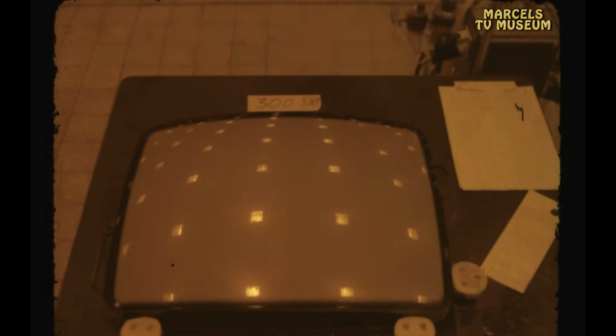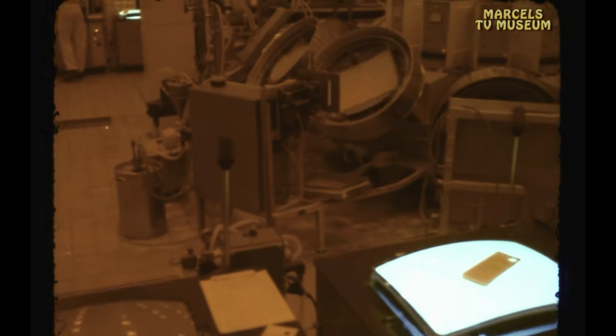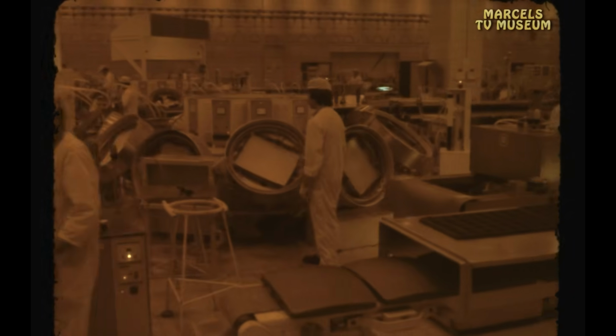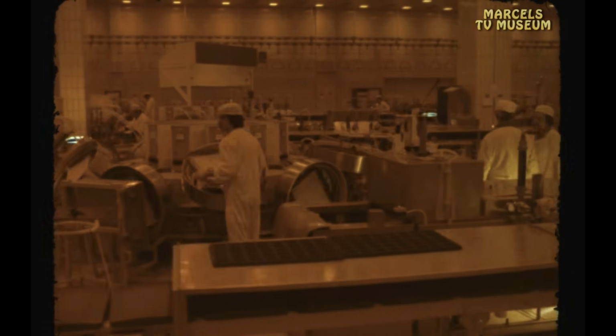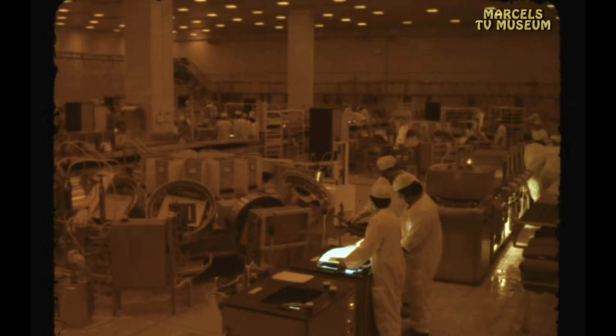Here, an accurate quantity of the fluorescent suspension for green is delivered into the rotating screen. The coating flows very evenly over the inside surface of the screen. That is why we call it flow coating. And the layer is dried under radiant heat. In the flow coat room, the fluorescent materials, which are products of our own research and manufacture, are applied to the screen in very clean conditions, where the temperature and humidity of the air are accurately controlled.